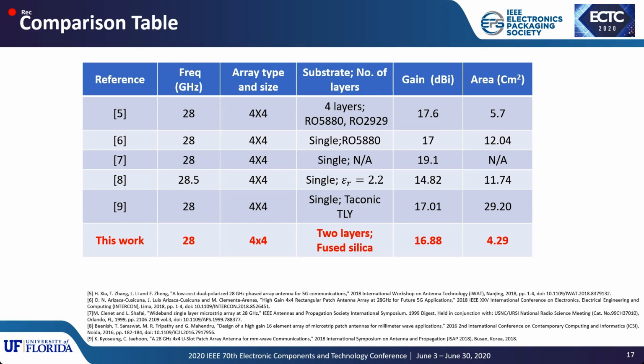So from this comparison table, it can be observed that different antennas targeting 28 gigahertz have been designed in the references, and the size of these antennas is typically 4 by 4, and different substrates like 4 layers and single layers are used for designing these structures. And from this work, you can see that the gain of these array antennas is close to the demonstrated work of array antennas on fused silica.